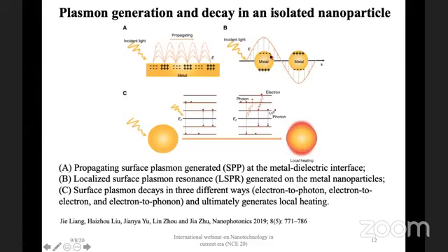Now these plasmons, when they are excited inside nanoparticles, produce a very intense electric field around these nanoparticles. As we have seen, there's a decaying electric field. In the case of nanoparticles, this field is very strong and it extends to a longer range. Now we can use this electric field to interact with the excitons. So we have quantum dots or semiconductor nanomaterials in the presence of the plasmon field, which can shift their optical or transport properties.